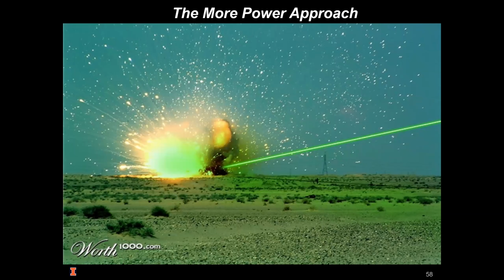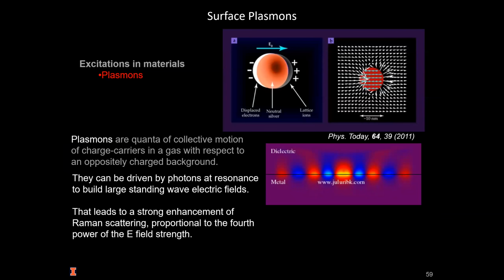But thankfully, there is another way to increase the signal without hugely increasing the acquisition time or the total laser power on the sample. The solution is to use plasmons. Because they can be driven at resonance by photons, they can be used to strongly enhance the electric field locally. Raman scattering is proportional to the fourth power of the electric field. So using this strategy, we can greatly enhance our signal.